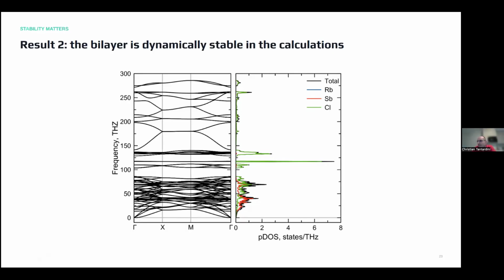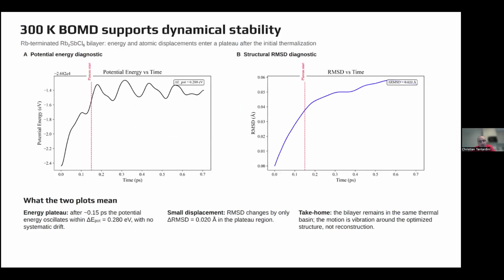But this is not enough, because we know from experiment that perovskites are easy to synthesize, and we have to be sure that they will resist temperature so that they will not degrade. So what we performed was Born-Oppenheimer molecular dynamics, where we increased the temperature for some picoseconds, and we looked at how the potential energy changes, and how the root mean square deviation of the atomic positions changes with time. What we have seen is that our bilayer is also dynamically stable, because at 300 Kelvin, so room temperature, people can synthesize and get this structure stable, so that it will not degrade.